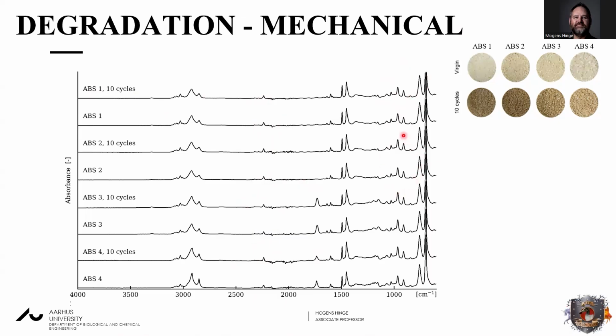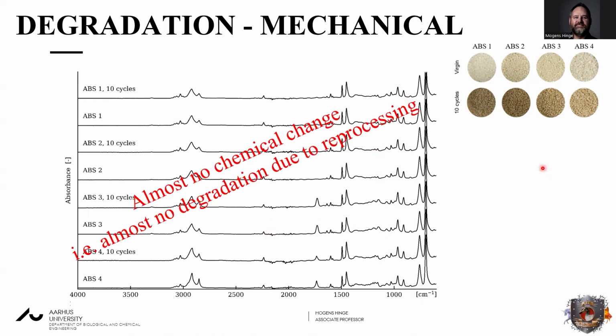Again, if we compare the pairs down here, you might see the same here. You might also see it, and down here again, you see it. So there might be a tiny, tiny change in the butadiene phase due to mechanical degradation. However, I think it's pretty safe to conclude that there's almost no chemical changes going on. And that means that we have almost no degradation due to reprocessing of the material.